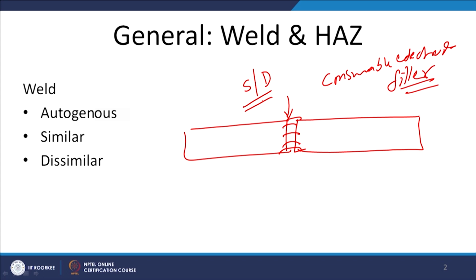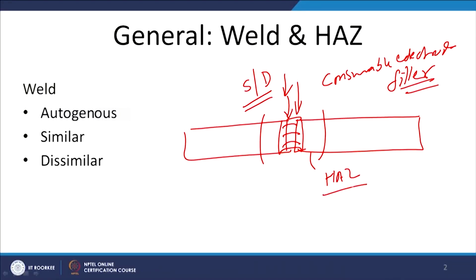But that allows us to use either similar or dissimilar metals to satisfy the requirement of the weld metal properties. But if we talk of the heat affected zone related aspects, then certainly whenever heat is supplied to facilitate the fusion of the faying surfaces, a zone near the weld metal is formed, and this heat affected zone we cannot do much to eliminate, because in fusion welding processes it is always there. Whenever heat is supplied to ensure the fusion of the faying surfaces, a heat affected zone is formed. The size of the heat affected zone certainly can be reduced by using high energy density welding processes like laser beam or electron beam, but this zone will still be there.